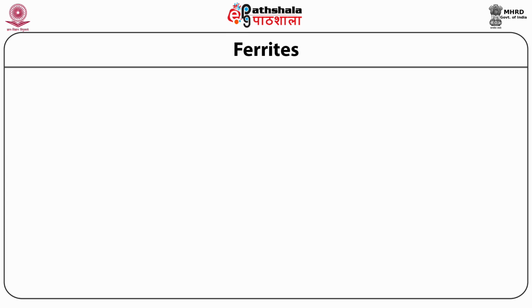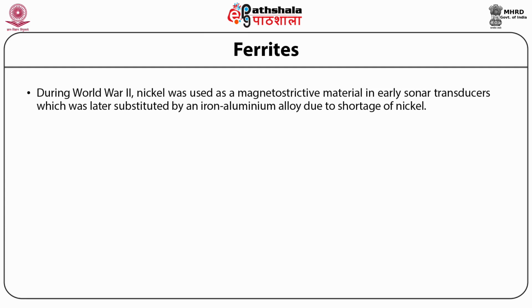Among pure elements, cobalt exhibits the largest room temperature magnetostriction of approximately 60 microstrains. During the Second World War, nickel was used as a magnetostrictive material in early sonar transducers, which was later substituted by an iron-aluminium alloy due to a shortage of nickel.